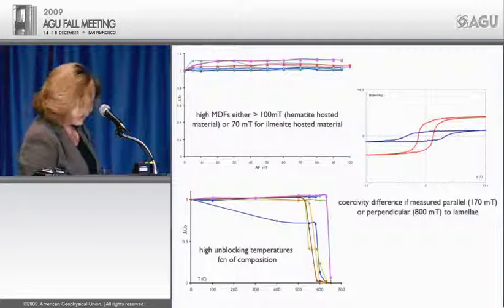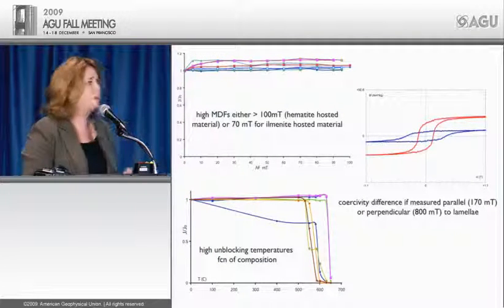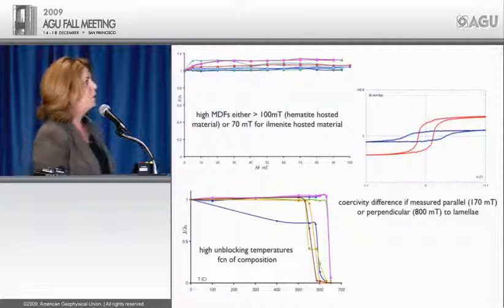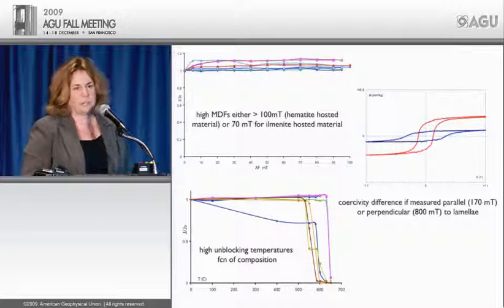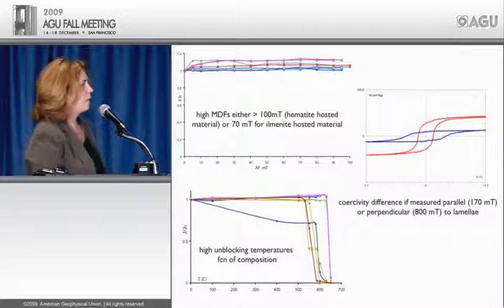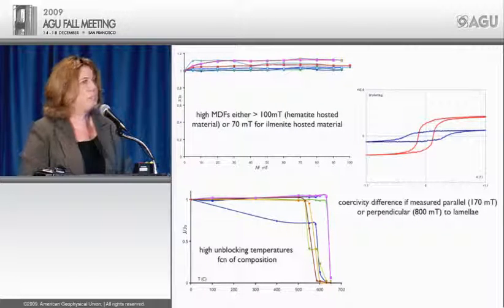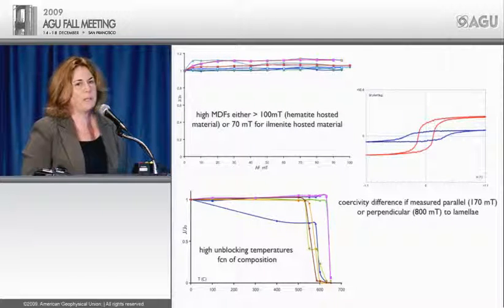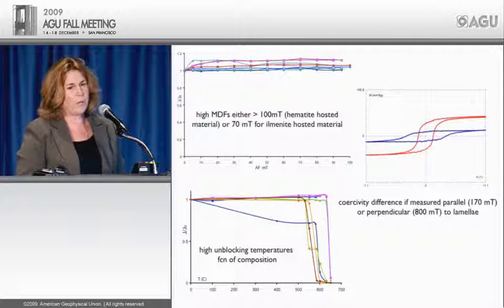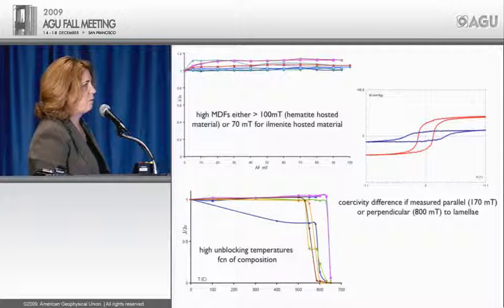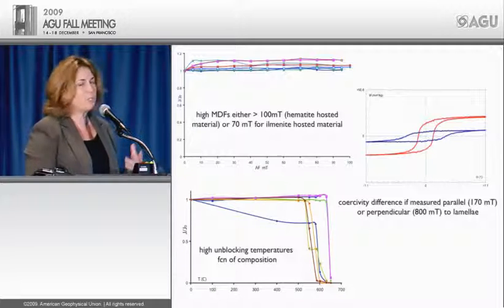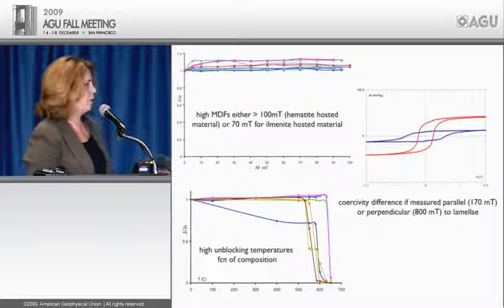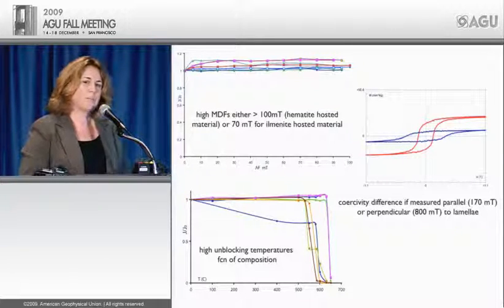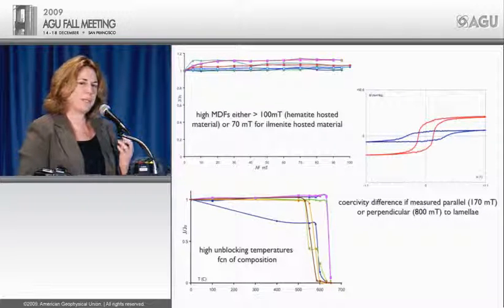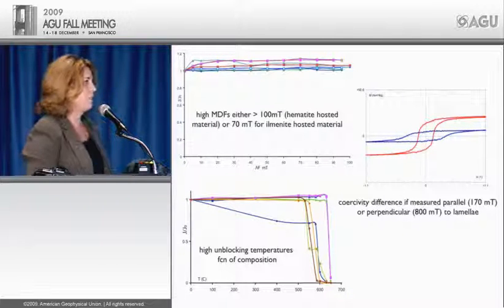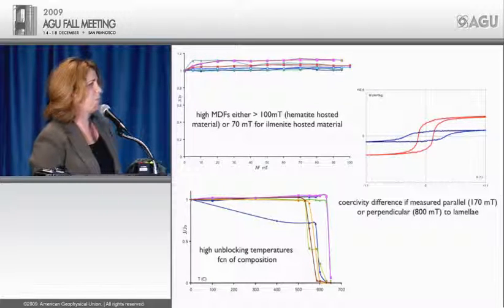Now, I'm not going to show many of these diagrams. I just have it to show you very similar properties for all this material. One, they're very hard to demagnetize. I think that's very evident. If you have a hematite-hosted material, you don't demagnetize them below 100 millitesla. If you have an ilmenite-hosted material, you start to demagnetize. You could have MDFs maybe starting around 70. So this is one reason why it keeps this memory for so long. We have a variation in blocking temperatures, and that's going to be due to the chemistry. What's the amount of titanium left in solid solution in the host hematite or the hematite lamellae?